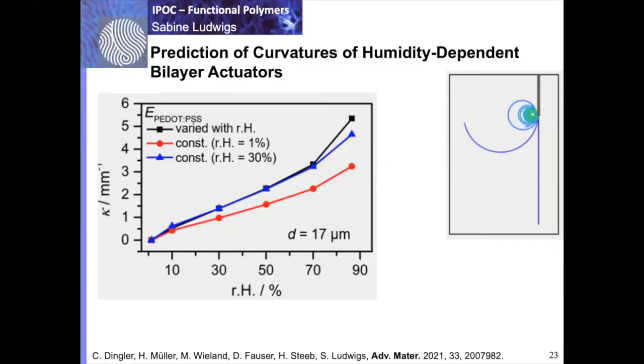And if we put all these parameters, which we experimentally determine, in the Timoshenko equation, then we can do these predictions. One example of such a prediction for these bilayers is this curvature as function of the relative humidity with a thickness of 17 micrometer of the whole bilayer. And the graphs here in black, red, and blue are shown for different input parameters of the Young's modulus for PEDOT:PSS. So let's take the completely dry one, that's at relative humidity 1%. So this shows this kind of curvature, which is not so realistic.